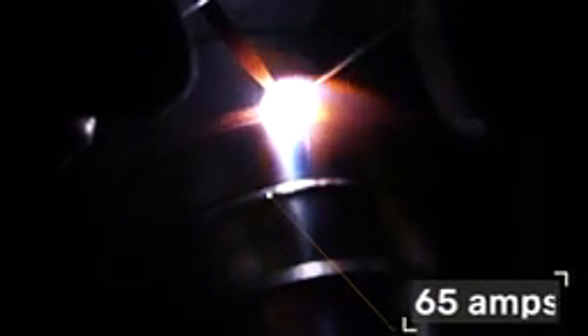I'll set my machine just a few percent over what I'll actually be welding. It makes being consistent easier for me than going wide open throttle. And trust me, I did the wide open throttle thing for a good while, but on thin wall tube, so much easier just to set your amperage maybe 10 amps above where you're actually going to be welding at. Here we are at 65 amps on the machine using some 3/32 or 2.4mm 2% thoriated tungsten.